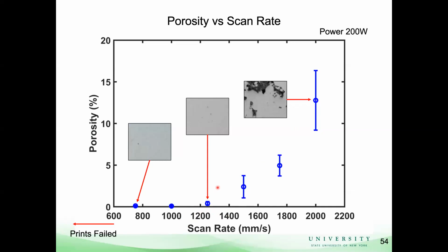Yeah, so that's a good question. We're keeping the laser power fixed, and then we're changing the speed at which the laser is moving across the surface. If we move it too fast, there won't be sufficient time to fully melt the whole layer and bond everything together. So there'll be these regions of incomplete fusion, and we'll have porosity from this incomplete fusion of the metal.